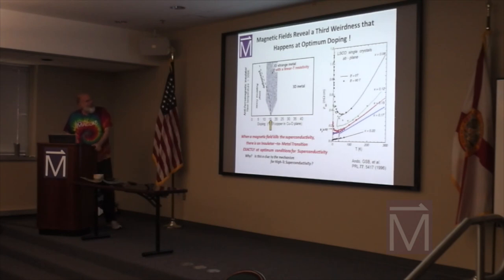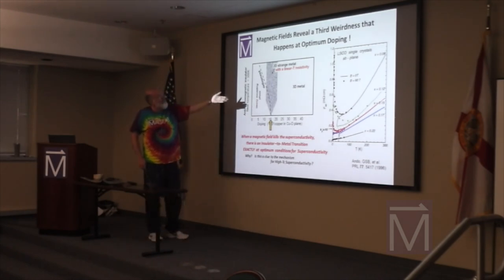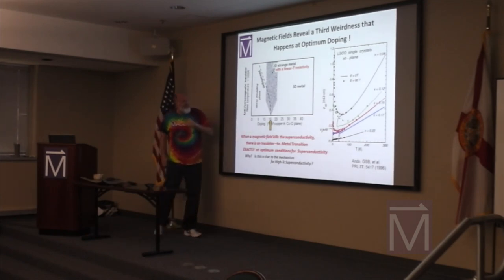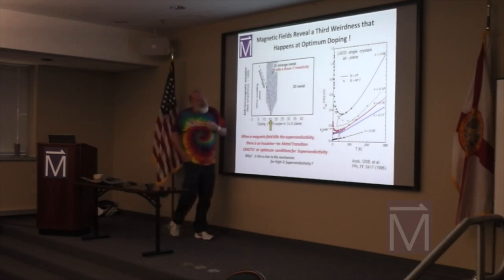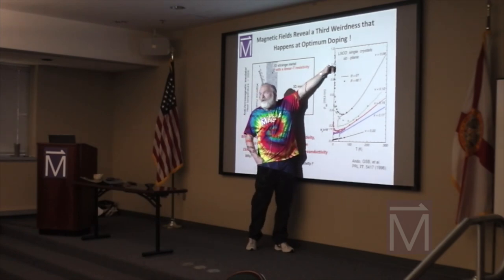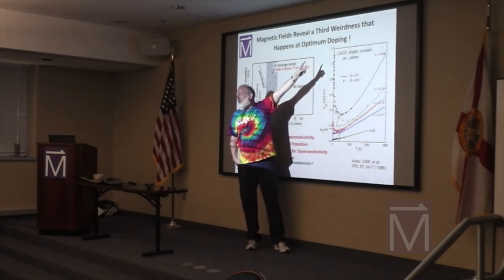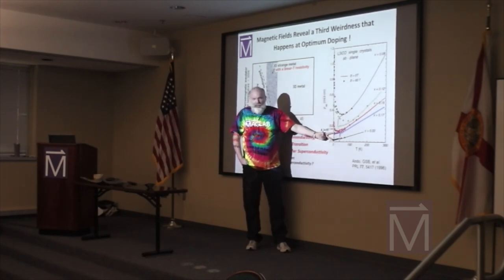We don't know why. So the goal of the experiments that I was doing back at Bell Labs was to build pulse magnets in our lab to see if there's a third weirdness that happens at optimum doping. Let's take a magnetic field and kill the superconductivity, because magnetic fields are the enemy of superconductivity, and see what happens. Well, the materials that have fewer removed electrons turn around and the resistance starts screaming up at low temperatures. That's what insulators do. They're going to have an infinite resistance to conducting electricity. The ones with larger doping, more electrons removed, stayed metals.